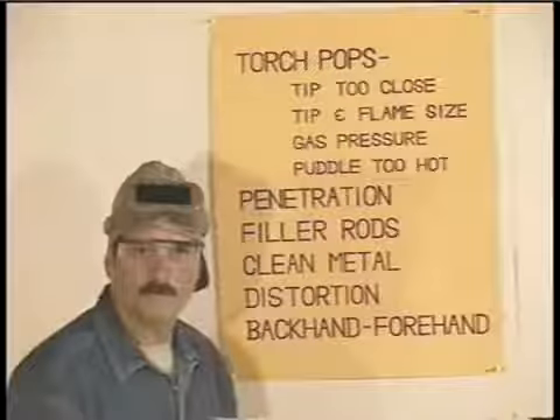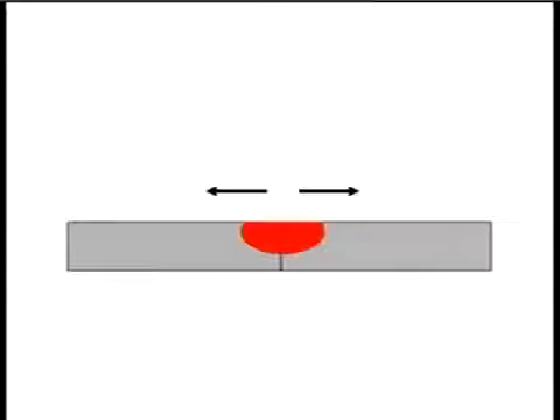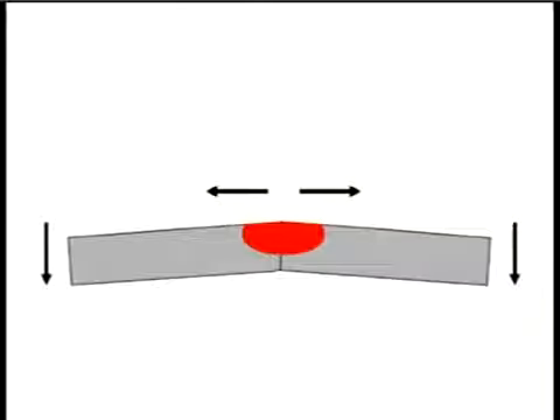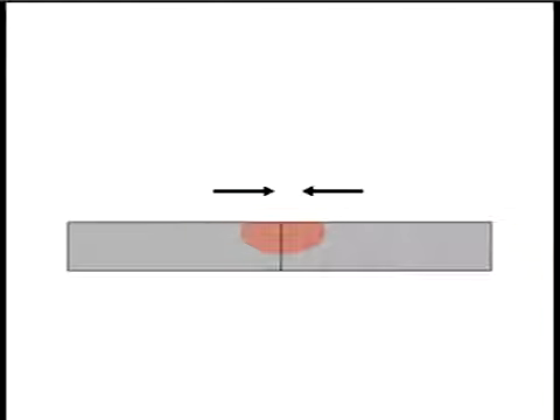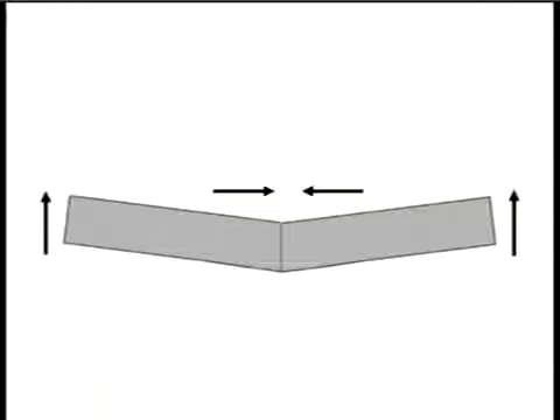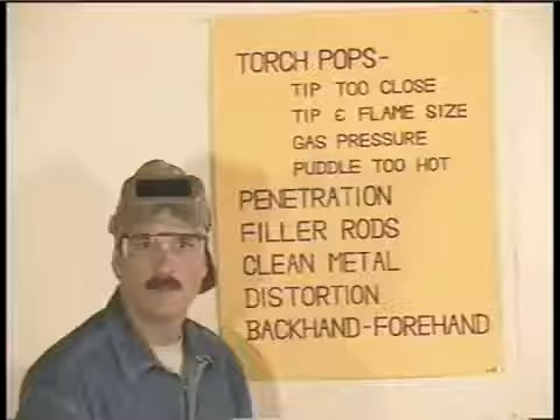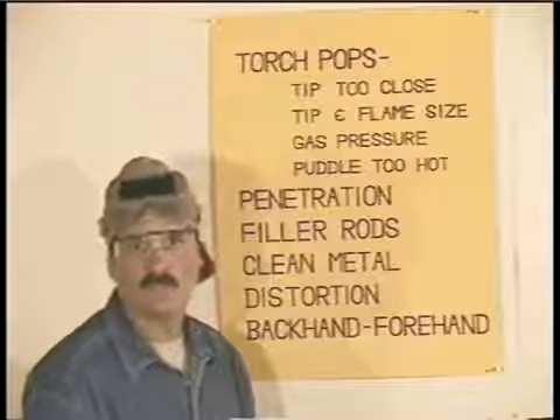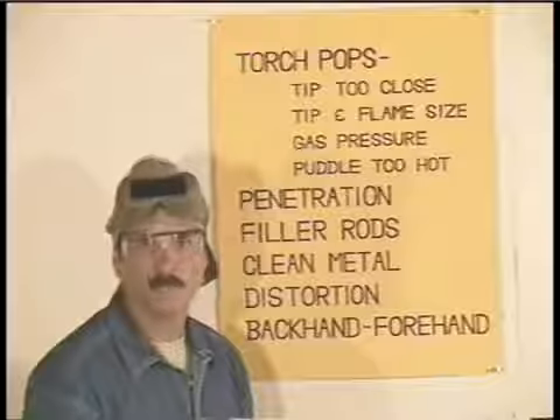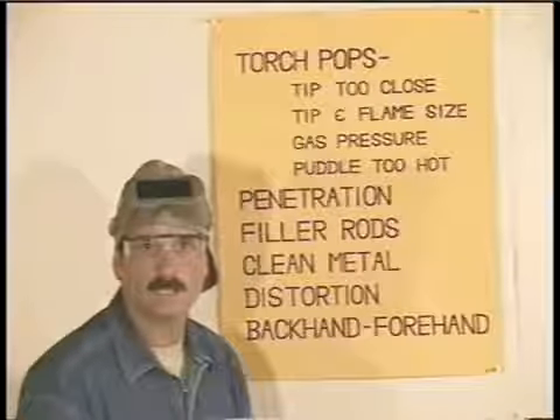It makes the welding a lot easier and you can do a nicer job. Distortion or warpage happens because when the metal gets hot, it expands. And when it cools, it contracts. And it contracts more than it expanded. The hotter the metal gets, the more movement you get. In oxyacetylene welding, the metal gets extremely hot because the progression of the weld is slow, and you're putting heat to the base metals for a relatively long time. When the base metals cool, they contract and warp, especially on larger pieces of thin metal.